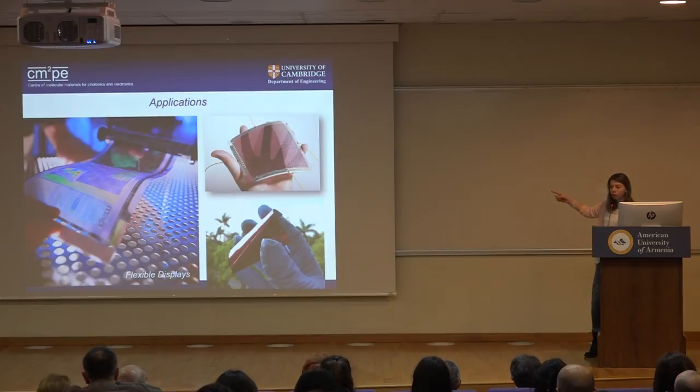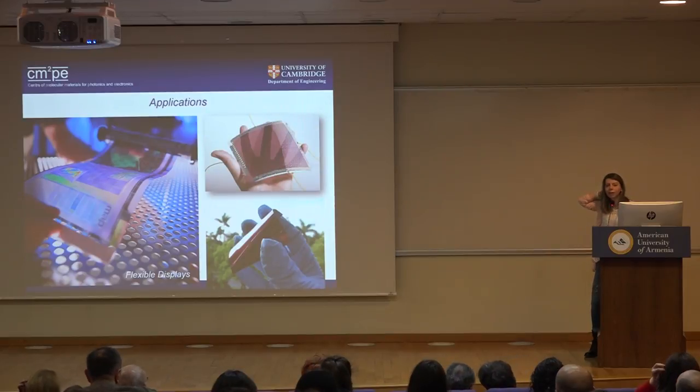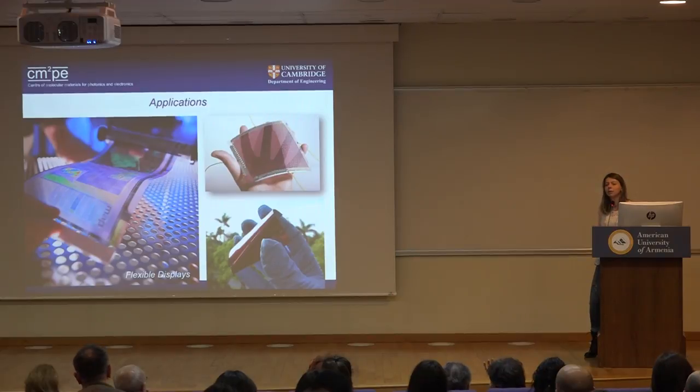And the other technology, obviously, is hybrid solar cells based on nano-engineered structures, and the best research in Cambridge University right now is around 8%. The best efficiency we are getting from polymer-based structures is 8%, which is quite impressive, because with silicon-based, the best one currently used is 24%, and we couldn't get higher for that. And with this set of properties and nano-engineered structures, so far we got 8%, and we still can grow and learn from our mistakes.